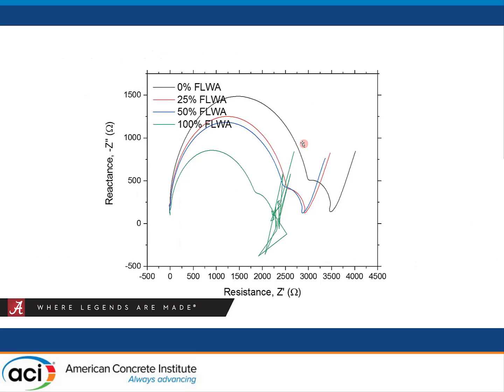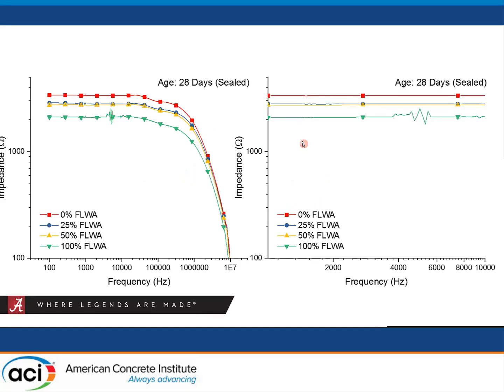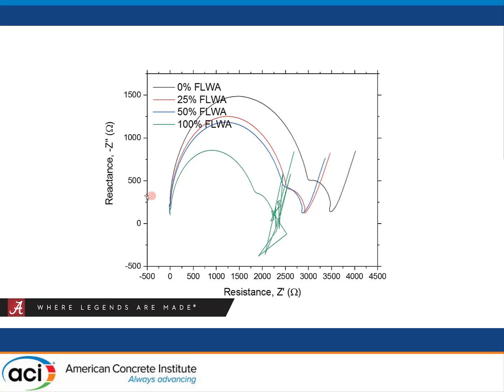And we can see that in our raw data when we look at a Nyquist plot of this right here. If we plot this on the Nyquist domain with resistance and reactance, we actually see this. These three curves here are kind of what we would expect. Actually, we wouldn't necessarily expect the second hump. That's another thing that we're dealing with. But we get this noise, and it's not good. And what's physically happening, the device, our impedance analyzer, can't actually balance the impedance because there's this residual effect present between our coupling medium and the bulk material.